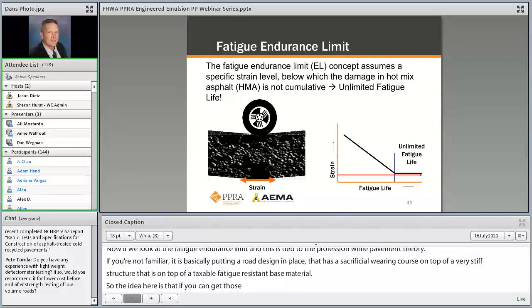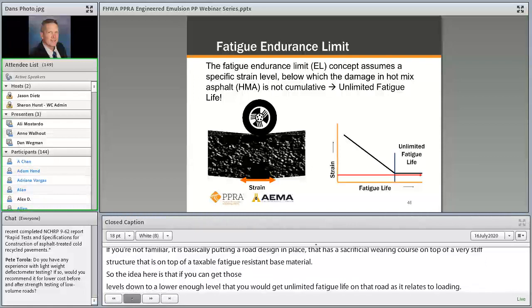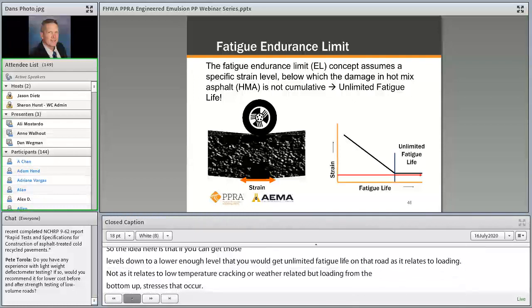Not as it relates to low temperature cracking or weather related, but as it relates to loading from the bottom-up stresses that occur. A lot of research was done for perpetual pavements, and for the most part the microstrain value that they came up with is somewhere between 100 and 200 microstrains, which is the level where you can see that fatigue endurance limit concept kicks in and you can reach that unlimited fatigue life.